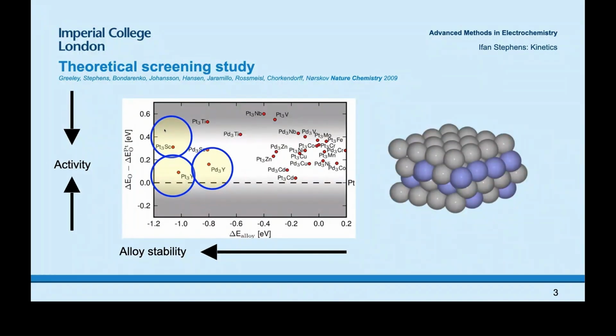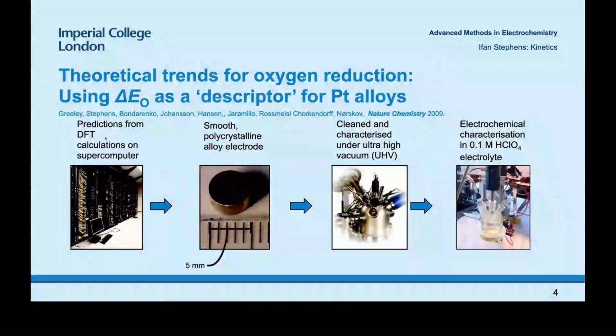I'll go into more detail about the fundamental insight we got from these experiments later on when I talk about combining experiments and theory in my later lecture. So essentially, this is the process we went through. We had predictions from density functional theory, then we made a smooth polycrystalline alloy electrode, about 5 millimeters in diameter. Then we sputter cleaned it under ultra high vacuum conditions. Then we put it into a rotating disc electrode setup, similar to the one that Anthony described earlier. We tested it in perchloric acid.